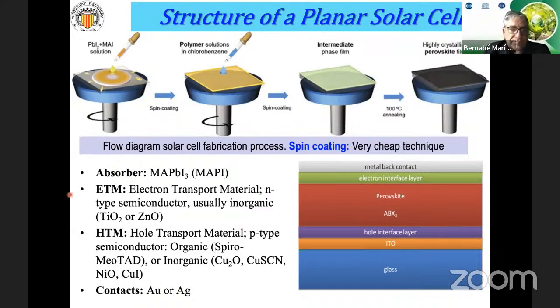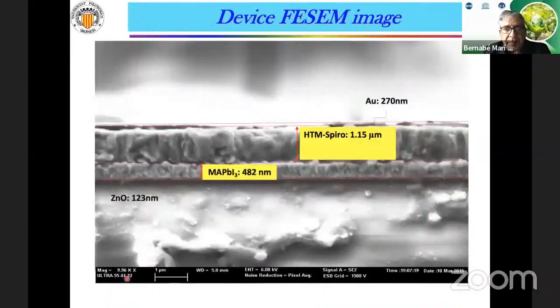Well, for the ETM, the electron transport layer, the best materials are titanium oxide or zinc oxide. And for the HTM, the hole transport material, which is a P-type semiconductor, we can use organic materials like spiro-OMeTAD, or inorganic ones like copper oxide, nickel oxide, or copper iodide. Well, here you have the field emission scanning electron microscope image of this kind of device. It's the substrate, zinc oxide, the absorber, and the spiro.